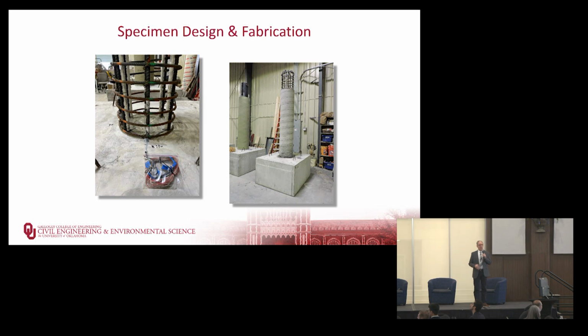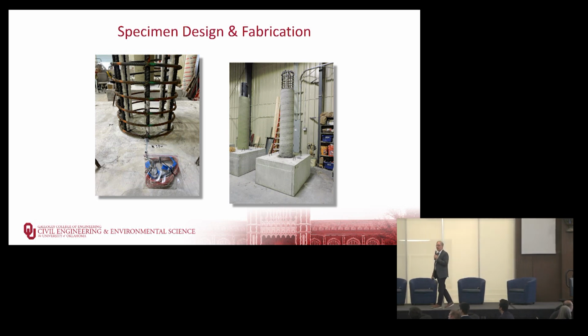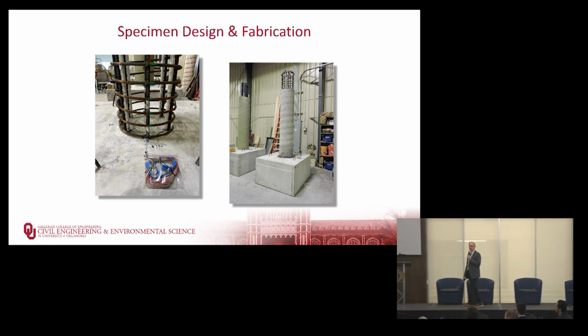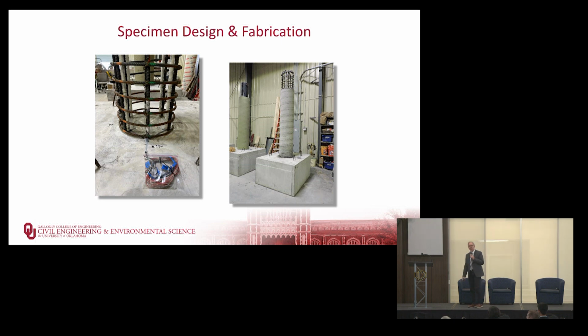And then because we were having to lay the columns on their side and test them, develop our own test frame, we wanted to make sure that it would give us results that were valid. So we also cast a couple reinforced concrete columns, just standard circular reinforced concrete columns, spiral tie, that we could test initially, compare it to previous research, when there's a ton of research on reinforced concrete to make sure our test frame was indeed testing them in a valid way.